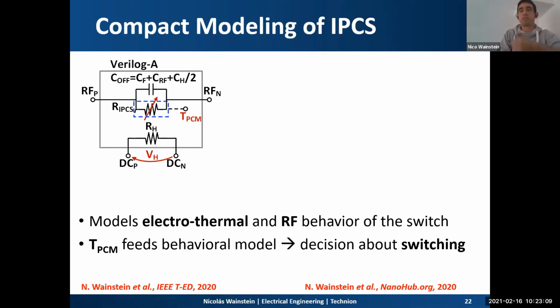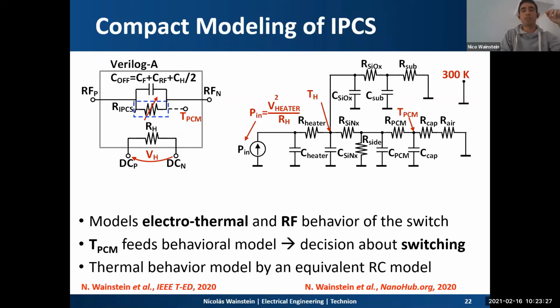Hence, we took this challenge and developed a compact model of the IPCS, and our model accurately describes the electro-thermal and RF behavior of the switch. There's a behavioral model that controls the resistance state, which changes as a function of the PCM temperature. And then the PCM temperature is estimated by an RC thermal equivalent model, where each layer is modeled by the thermal resistance and thermal capacitance, being the heater the heat source. Then, as we can see here, the different layers: this will be the dielectric 2, silicon nitride layer, modeled by its thermal resistance and thermal capacitance, the thermal resistance and capacitance of the PCM, and the capping layer. And to the bottom, you will see the thermal capacitance and resistance of the dielectric 1, which is silicon oxide,